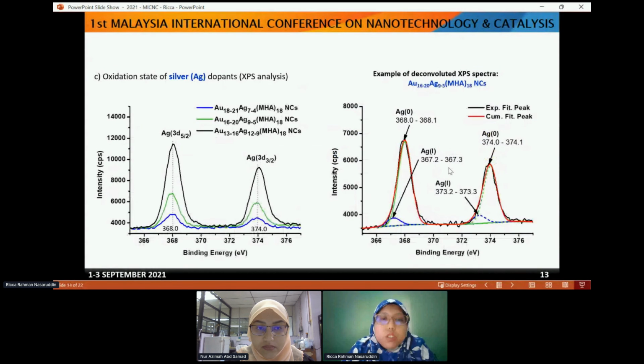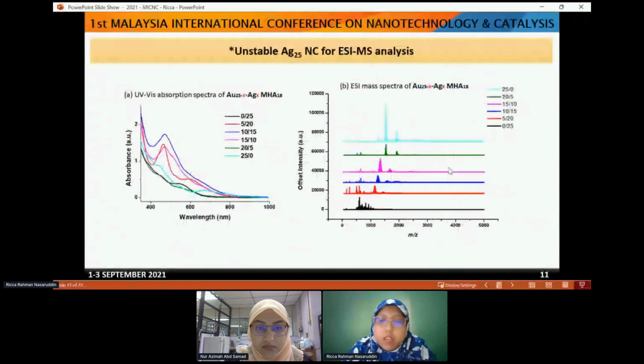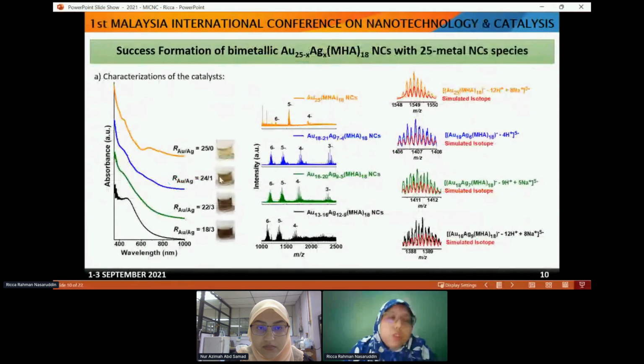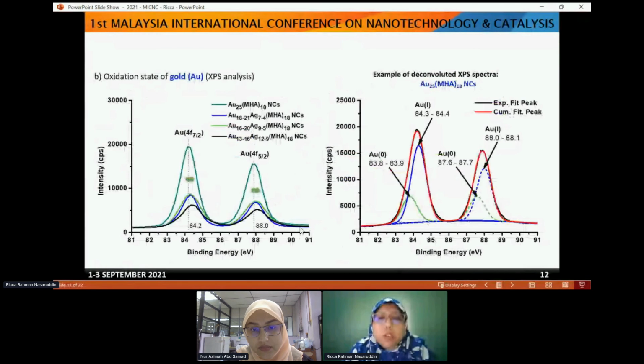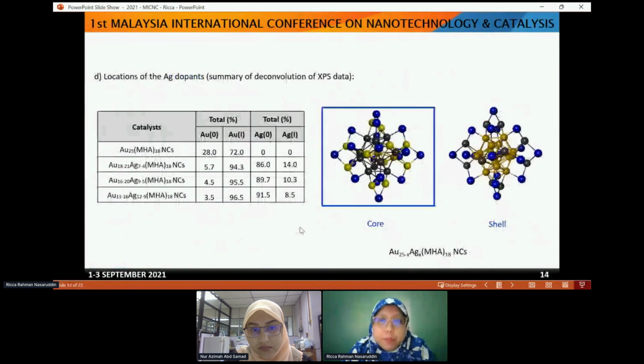Returning to the UV-vis spectroscopy, if you look carefully, the peak at 670 disappears faster as compared to the peak at 450. This shows that the disturbance occurs at the core rather than at the staple motif. So UV-vis also supports our justification.